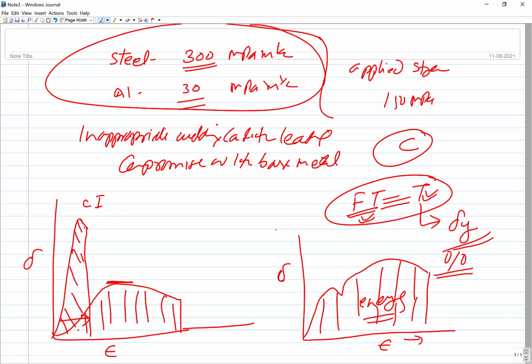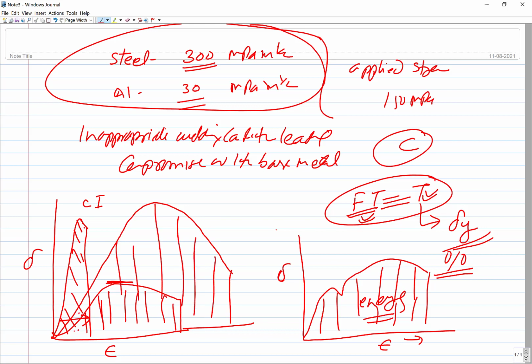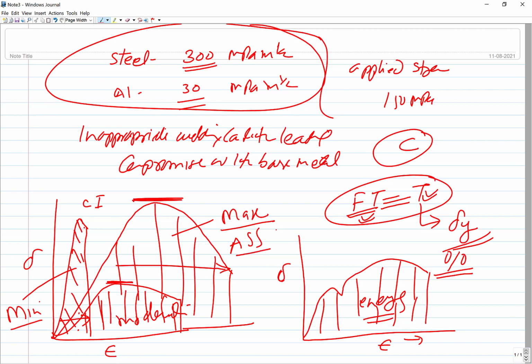If you take the third case where strength is also good and ductility is also good, you see not just strength but long elongation, significant elongation prior to the fracture. So in this case the energy absorbed will be maximum, in this case it will be minimum, and here it will be moderate. This may be the case of your austenitic stainless steel, this may be the case of cast iron, and for other steels like medium carbon steel, this may be the case.